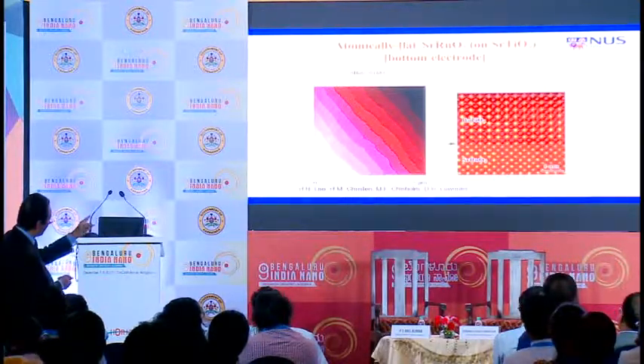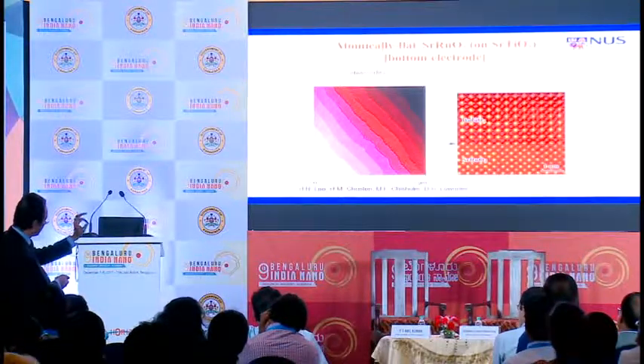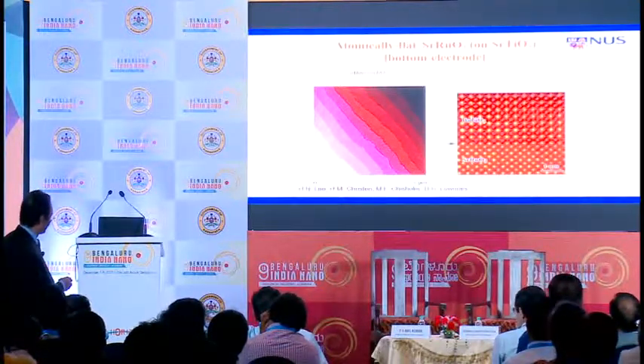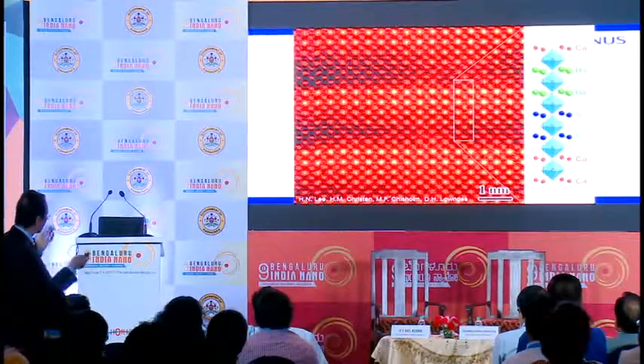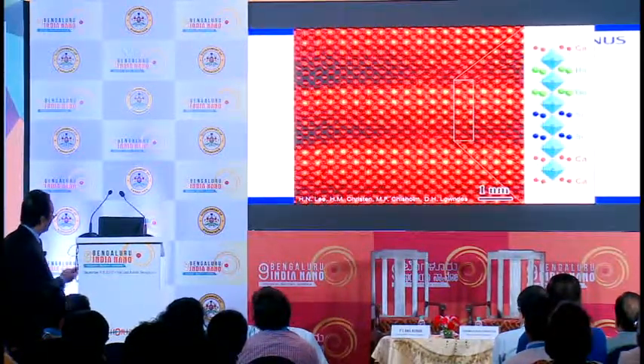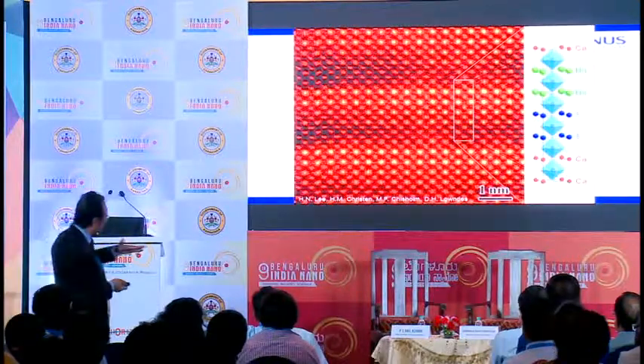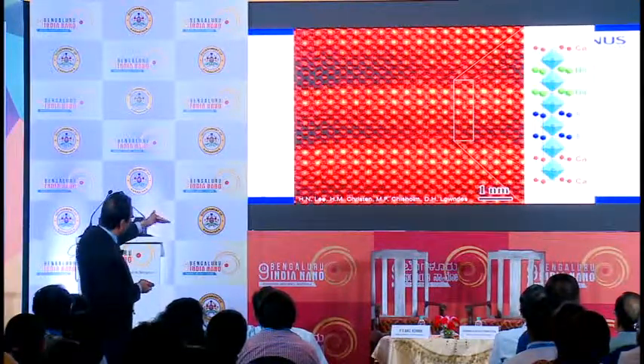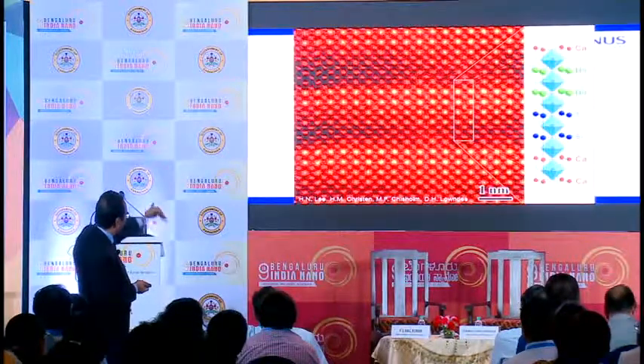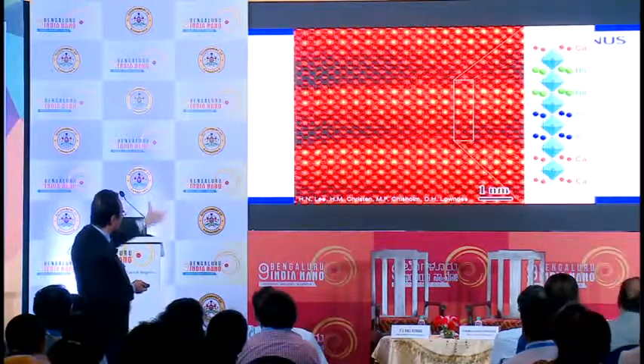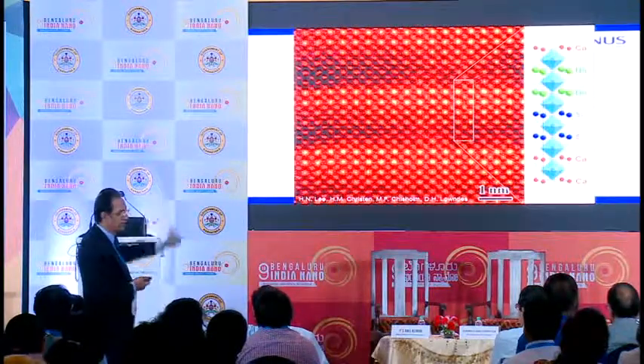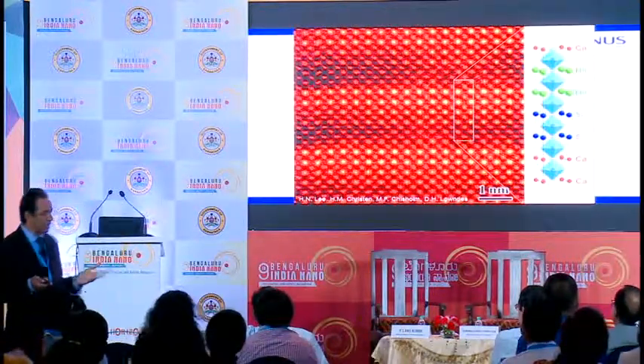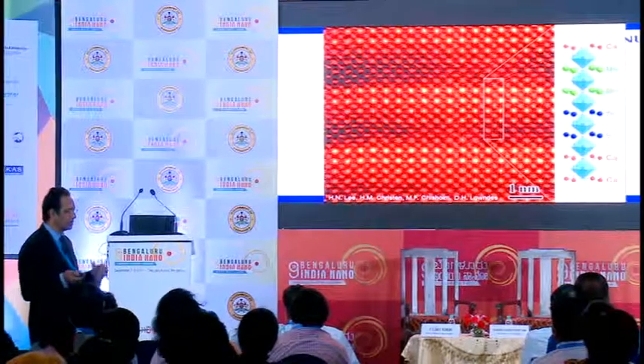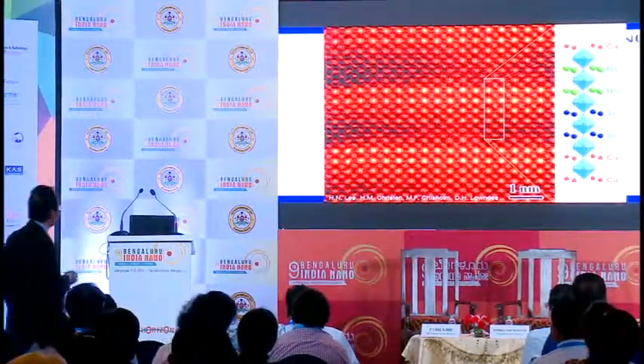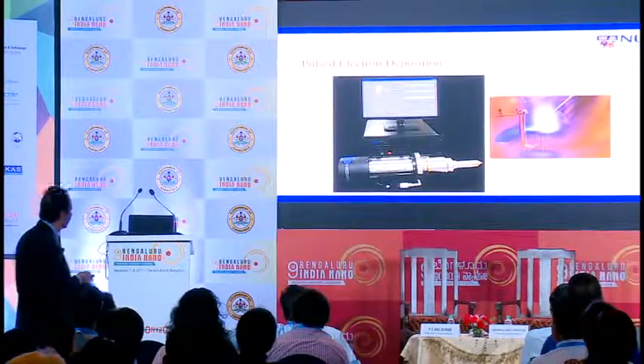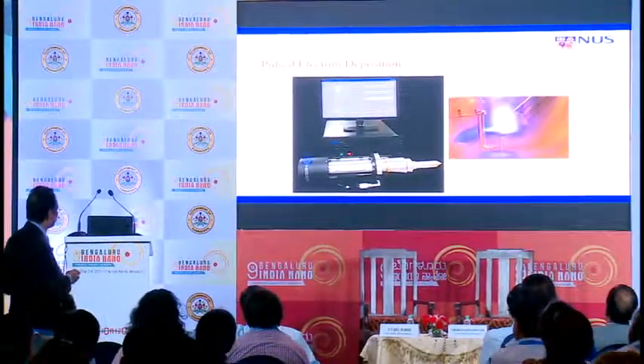The bright dot to bright dot spacing is roughly 4 angstroms. You can also make completely new materials that don't exist in nature. Here, for example, is one atomic layer of calcium oxide, and then you put another calcium oxide, then you put strontium oxide. So this material doesn't exist in nature, but you can create something like this. And now you can start to do what's called block by block growth of oxide and create totally new material that didn't exist before.